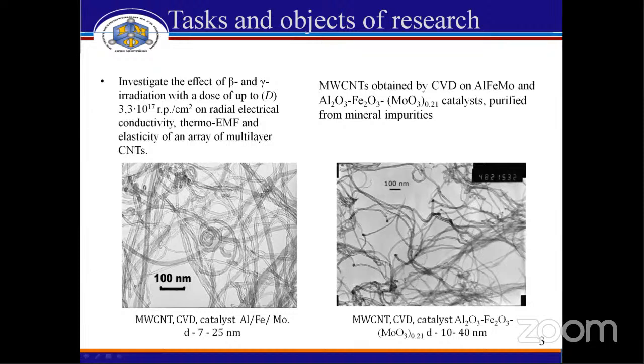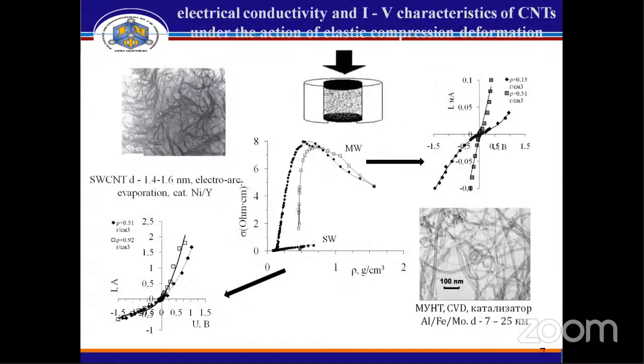These are examples of photos with different catalysts. Carbon nanotubes in a bulk state are not electrically conductive, and for transition to the electrically conductive state, it is necessary to establish an electrical contact both between neighboring nanotubes and with electrodes. Therefore, CNT were placed in a dielectric cylinder under a piston. With a decrease in volume, the circuit between the electrodes closed and the system passed into the electrically conducting state, which corresponds to the dielectric-metal transition and is accompanied by a sharp increase in electrical conductivity as a result of reorientation of CNT and their compression. Then it reaches a maximum and with subsequent compression smoothly decreases.